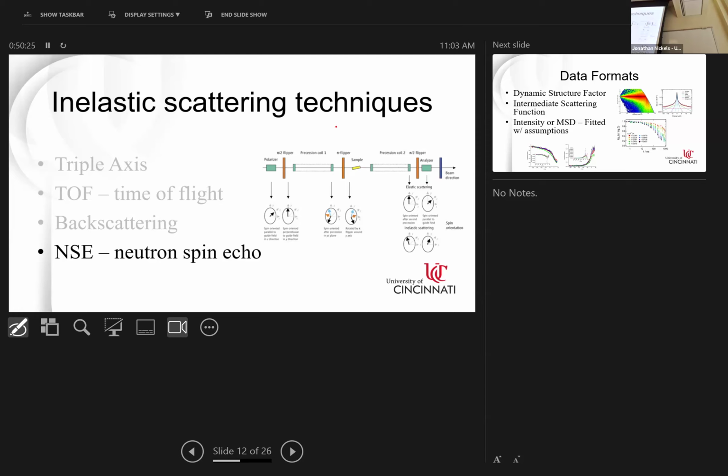So this would pick up, yes, you could see picosecond motions with spin echo, but its uniqueness is in the fact that it can see out to hundreds of nanoseconds. In that case, it really would be things like, okay, let's put a polymer melt in the spectrometer, and I want to see the relaxation time of the chain relative to the relaxation time of the side chain. So there's the backbone, that's covering flow. The side chains might be covering diffusion, right?